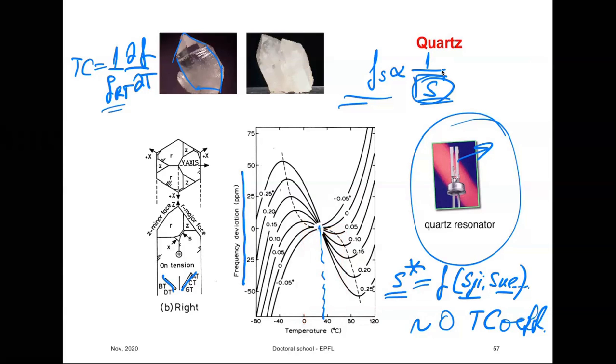You will find very often in electronic equipment that its best operation temperature is between, let's say, 0 and 30, 40 degrees or something like that. And one of the reasons is that many components have properties that will change with the temperature. So in single crystals, you can control this by making different cuts. So here is one of the examples where these Euler transformations are useful.